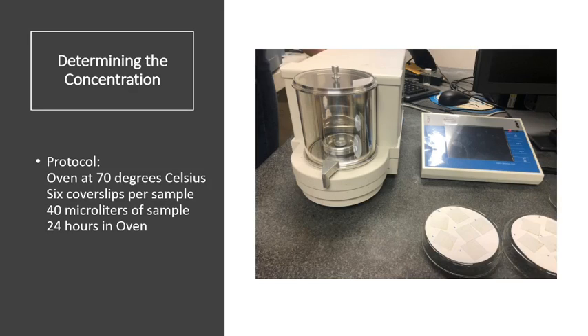We needed to determine the concentration of these samples as well. So we used 6 cover slips per sample, and we would mass those here on this machine. And after we massed them, we would put 40 microliters of our graphene quantum dot sample onto each of the cover slips, and then we put it in an oven for 24 hours. After 24 hours, the water had evaporated from the sample, and we were left with just those quantum dots, and we were able to mass them again and determine their concentration mathematically.